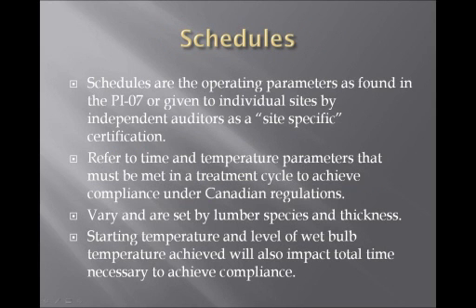Schedules are something that you'll hear a lot of talk about, and they're the operating parameters found in the PI-07 or given to individual sites by a site-specific auditor. What these schedules refer to is the time and temperature that must be met in the treatment cycle to achieve the compliance for Canadian regulations. They vary by lumber species, they vary by lumber thickness, and if you are going to operate and treat with your chamber a multitude of sizes, you're going to need to be familiar with multiple cycles. They can be influenced by the start temperature, which must be 15 degrees Celsius, and the level of wet bulb achieved, and you can also vary the time by playing with levels of wet bulb, the top end of that temperature, etc.